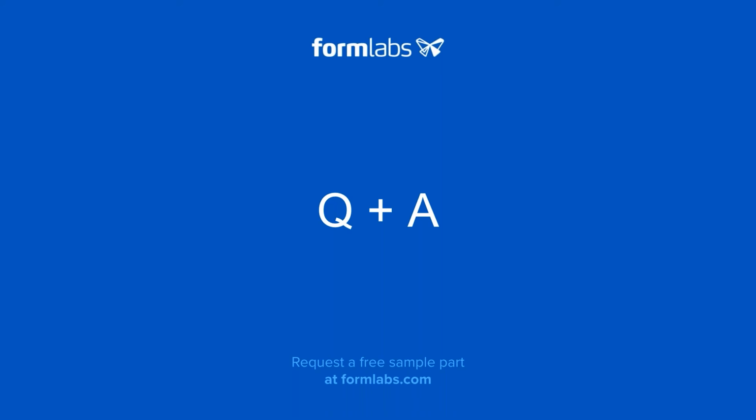So yes, it's a great question because it's quite important to think before you print that your model will not have perfect dimensional accuracy. It's pretty good actually. Our users are pretty happy about it, but what we recommend is to give a little bit of extra stock in the mold and then hand sand it at the end so that you have the perfect dimension that fits. But usually the critical molding surfaces don't need to be hand sanded, it's more to fit both halves of the mold together and fit it in the metallic frame.